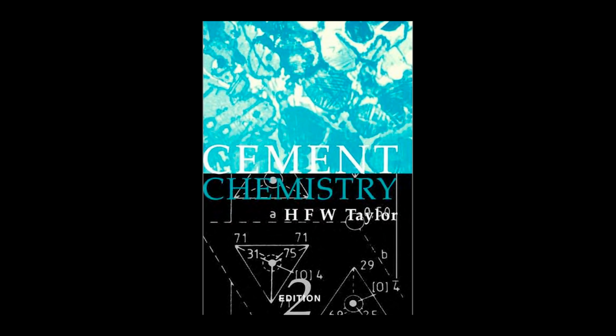ASR is often called concrete cancer because it's a self-propagating durability failure. It's a chemical conflict between the cement and the aggregate. It's a reaction of massive volumetric change. It involves reactive silica phases, amorphous silica, opal, things like that, in the aggregate reacting with the high alkali concentrations, particularly the hydroxide ions, present in the cement pore solution. This chemical process generates a hygroscopic, swelling alkali silicate gel. And this gel expands with tremendous force. It absorbs water, it swells, and it generates immense internal pressure, far exceeding the tensile strength of the concrete. This pressure manifests as a characteristic map cracking pattern on the surface and significant internal damage, reducing strength and providing pathways for further chemical attack.